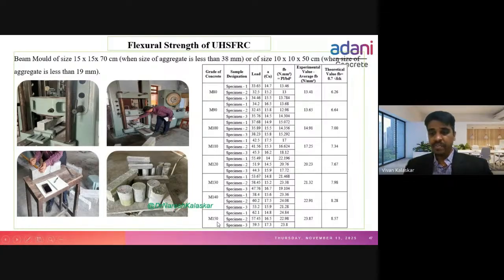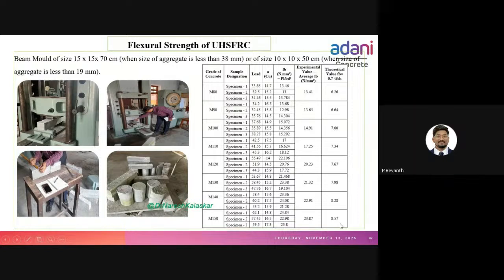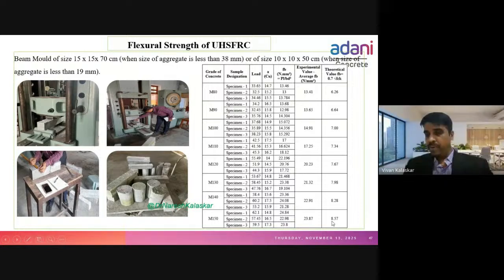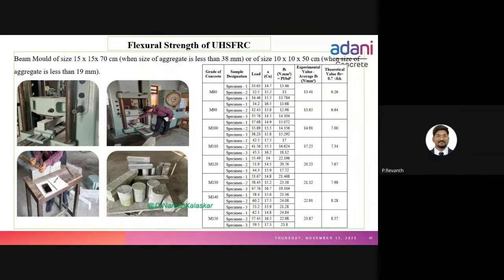If you take M150, the code specified formula will give 8.57 flexural strength, but we got 23.87. We can say 24 MPa of flexural strength. So we can see the flexural behavior of ultra high performance concrete when comparing with